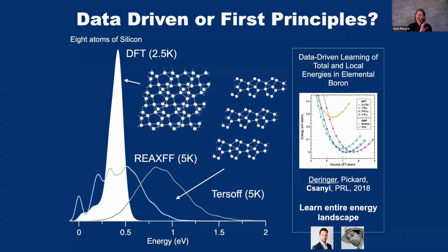Now, this is going to be relevant for later on. I've emphasized that I was using plane wave density functional theory for doing these searches. But traditionally, the field of crystal structure prediction relied on fast empirical potentials because it was felt that that's the only way to get the correct sampling of structure space. But here I'm just showing an example of why crystal structure prediction probably was thought of as difficult for people using empirical potentials. That's because of the old style of empirical potentials, for example, here we have a Tersoff potential for silicon versus density functional theory.